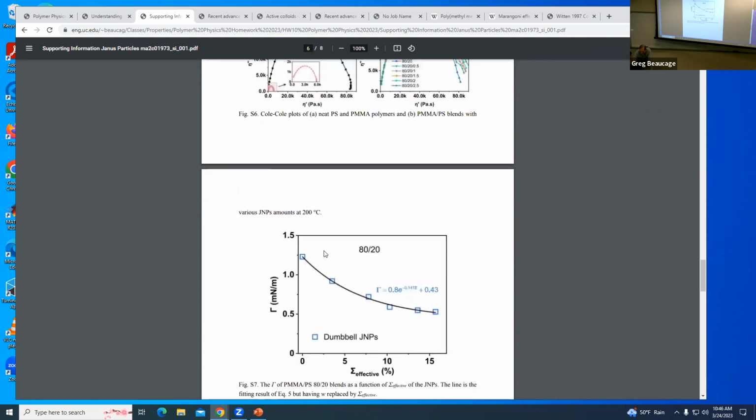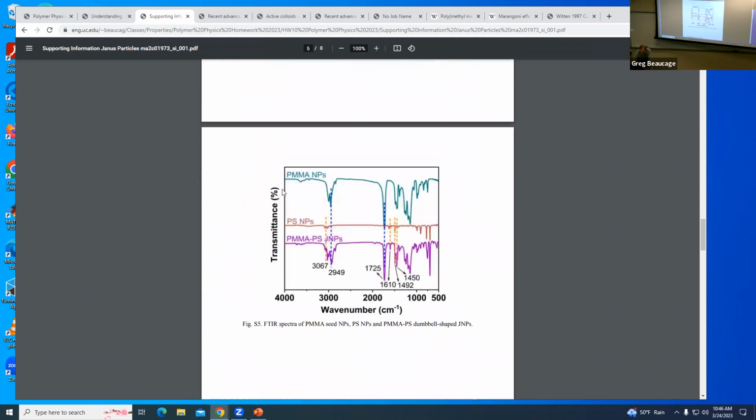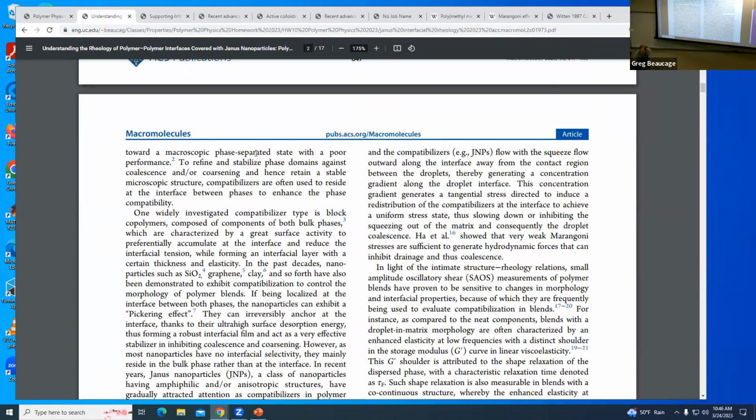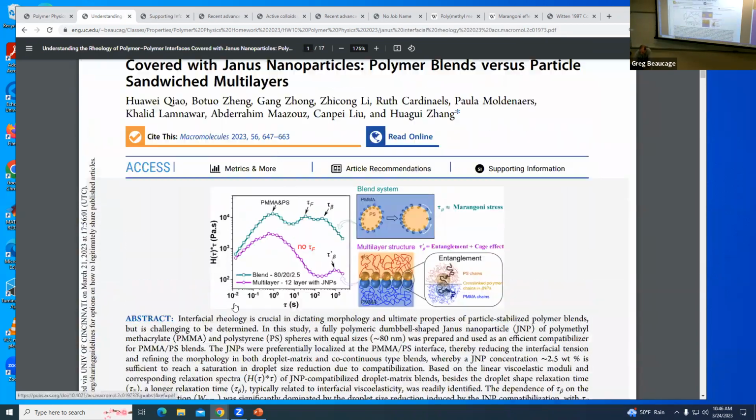And then, all right, he does this other thing. Normally, if you wanted to get this wide spectrum, look at his range here. He goes down to 10 to the minus 2 seconds, and then he goes up to 10 to the 3. So he's got like 5, 10 orders of magnitude, right? That's too much. In one measurement, you get one order. If you just do one temperature and do oscillatory, you get 1 decade in frequency, maybe 1.5. So if you want to get more, usually you change the temperature. So you do time-temperature superposition, and you can move the things around.